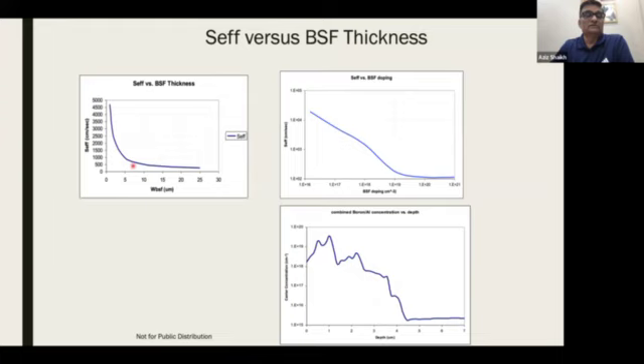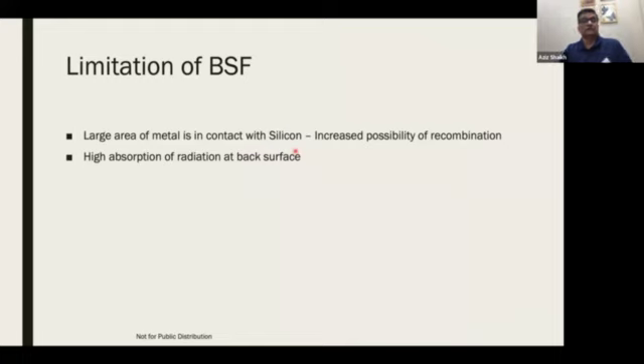If you have about 10 microns, which is normally 8 to 10 micron for the back surface field, you have about 500 centimeter per second. So you are reducing it 10 times, and that gives you improvement in efficiency. The other factor is how strong your back surface field is, which is given by the doping concentration within the back surface field area. The stronger the back surface field, the lower the recombination velocity. So it is a combination of that.